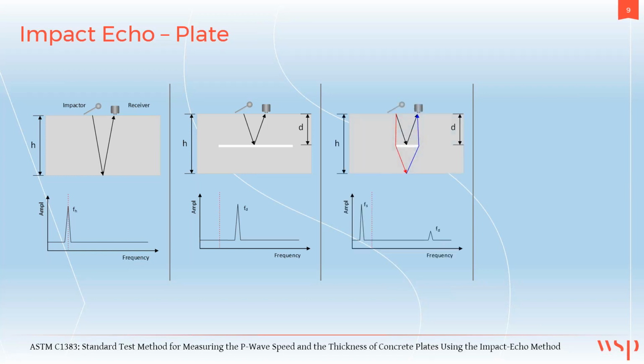If the defect is rather small, you may get a mixed mode response in which part of the signal is reflected from the embedded defect at depth d, and the other part reflects off of the far wall of the element. And so you get multiple peaks in the response in the frequency domain below.